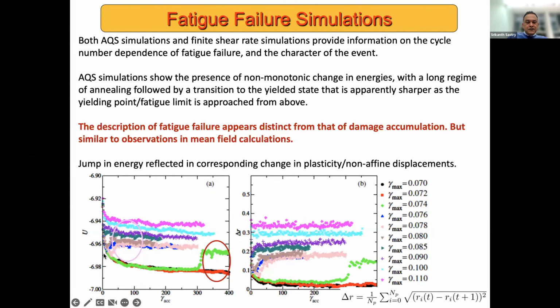And so this seems to suggest that there are two parts to the response of a glass. One is mechanical annealing, and this is always something that happens. And in addition, there are these failure events that are triggered somehow, and this is something that we don't yet have a very good handle on. And these are very sudden events at later times, okay?